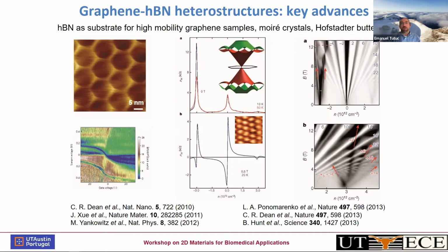And as such, it provides a very clean neighboring environment for the electrons in graphene. And as a result, electrons in graphene encapsulated in hexagonal boron nitride have a mobility that is high, typically 100,000 centimeters squared per volt second. It's common at low temperatures, but even higher values have been reported.